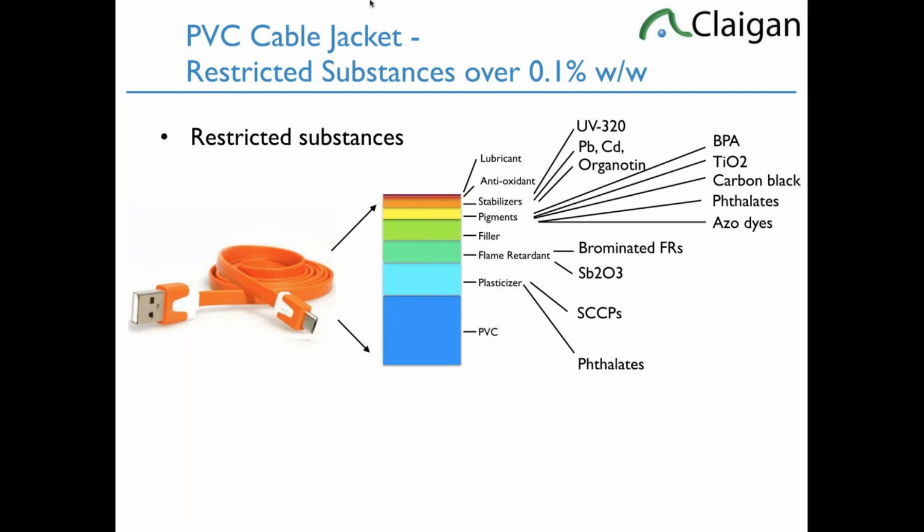The pigments can have their own plasticizer, and that's where we get a lot of low concentration, 2,000 or 3,000 ppm non-compliances for phthalates. It can have its own antioxidant, usually really low concentration though, not normally a failure. They can have azo dyes, infrequently in plastics, more likely in other things. Pigments have this tremendous ability to be non-compliant.